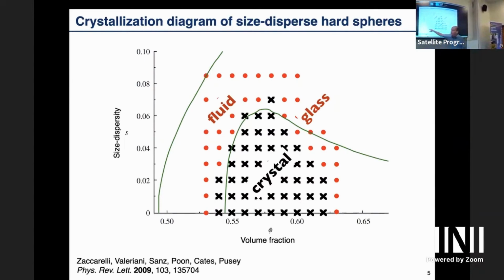Here you just have density, and then you have a fluid. So the system is disordered. As you increase it, between 50 and 55%, there is a coexistence. 49 to 54 is a coexistence, but in simulation, starting at 54%, you get hard sphere crystallization. And if you actually start the simulation at 60, I think to 63 or higher, it's already jammed, so you cannot actually study crystallization in simulation.